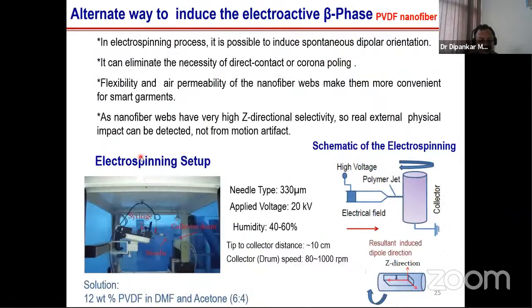There is another way to make the beta phase, like the electrospinning setup. The electrospinning setup is a very simple setup, but one has to apply a very high electric field between the tip and collector. This is the metallic collector and this is the metallic tip. If we put the polymer solution here, and give the syringe pump this side, and apply a very high electric field like 10 kV or 20 kV, then if we give pressure here, you will get a spray. So you'll get the polymer jet.